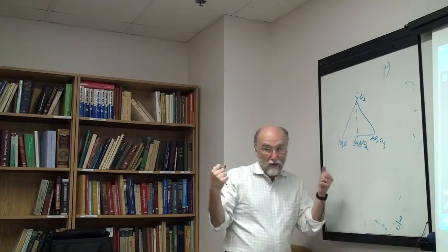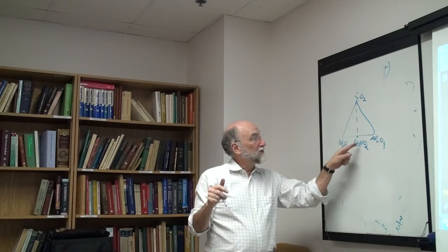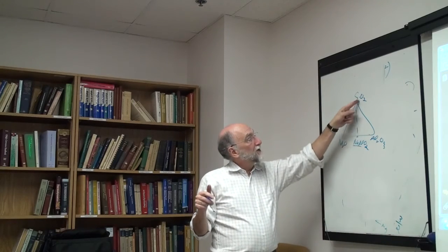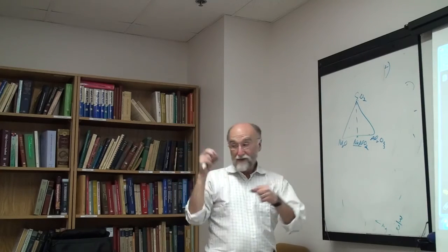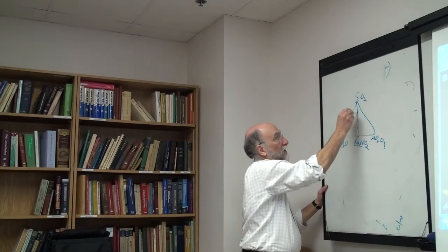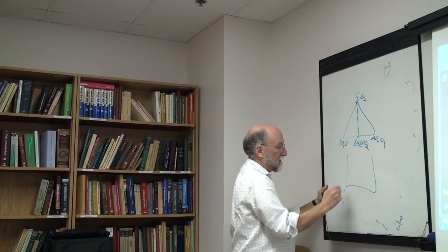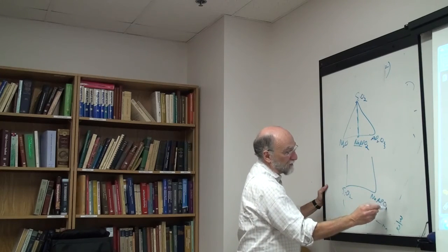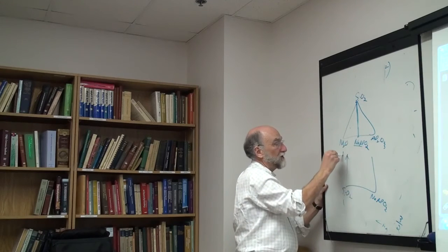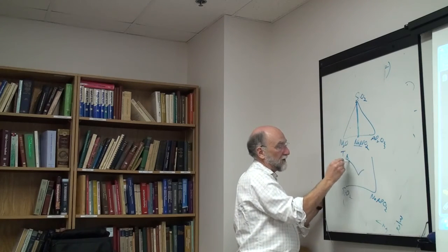Remember I said the sodium and aluminum come together, the aluminum occupies the silicon sites with the sodium staying next to it to compensate the charge, so it's really going in as a single particle. So then we looked along this line here, so if you treat this as SiO2 going to NaAlO2, this is the section along here versus temperature. We had a phase diagram that looked like that.